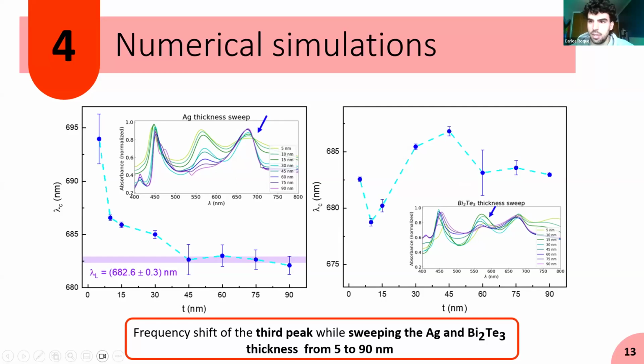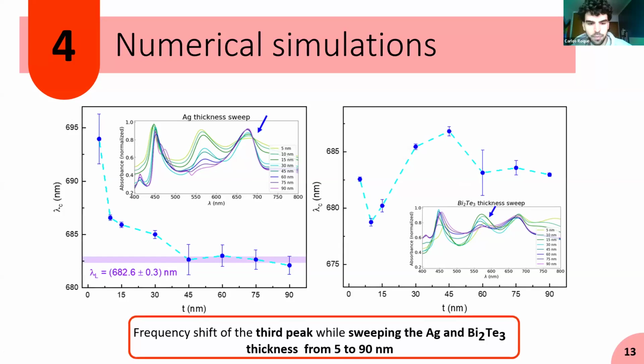So we believe that this is a plasmon that is excited in the interface between silver and air or silver and the substrate, whereas the other previous two are excited with the silver interface with the bismuth telluride. As there is no reported literature data from gratings with these two materials, we believe that that's the case.